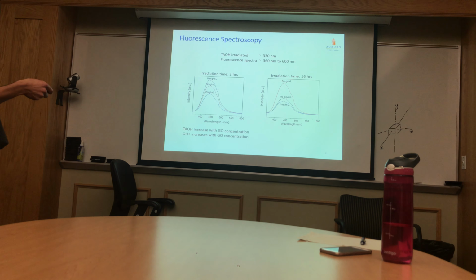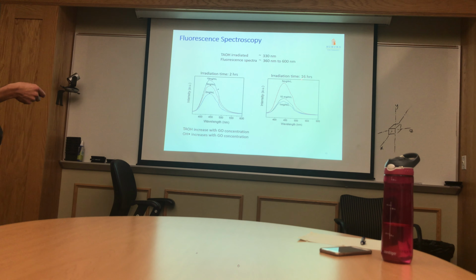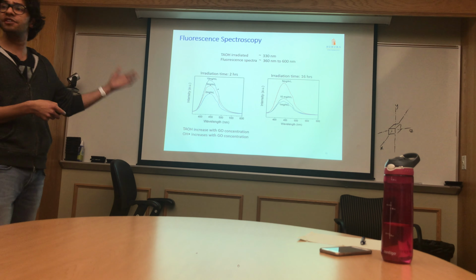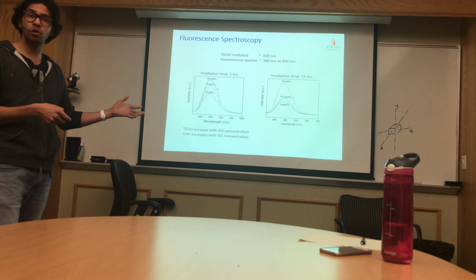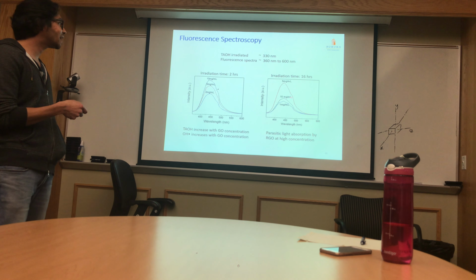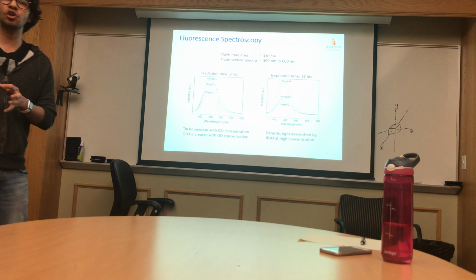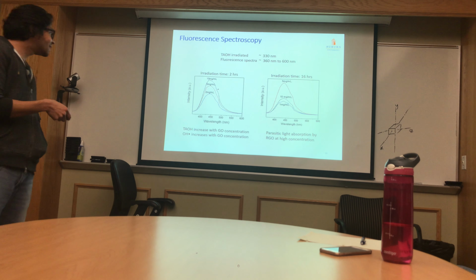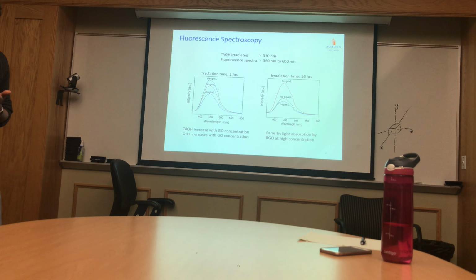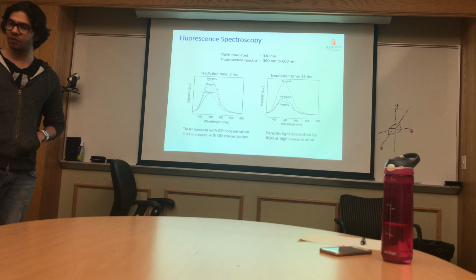Now, in the second plot, we irradiated our GO plus TA sample for 24 hours. However, the trend changed here. Here, 5 milligram per milliliter concentration shows the highest fluorescence. The reason for this was that there was parasitic light absorption by RGO at high concentration, and hence not all of the GO was able to reduce. So these results prove that yes, TAOH was formed, and yes, OH free radical is formed during the photoreduction step. Another thing we need to keep in mind when designing a photoreduction system is the concentration of GO, because of the parasitic light absorption at high concentration.